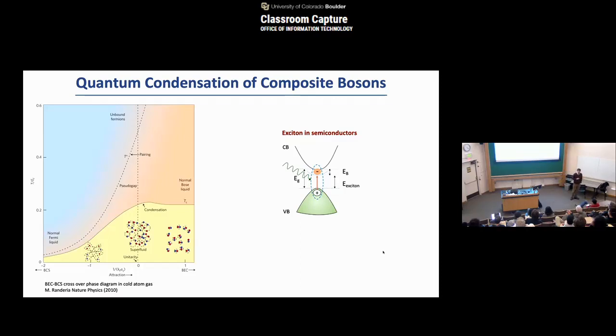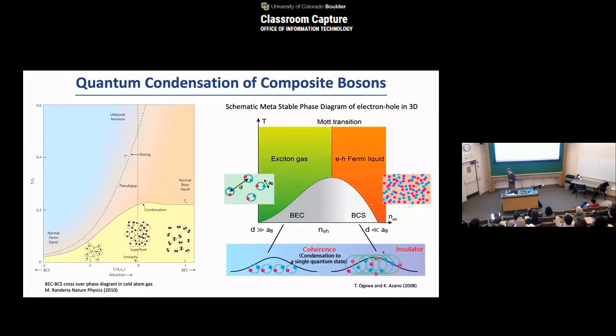Of course, the exciton as an excited state has a finite lifetime. But somehow, with some magic, if we make this exciton lifetime long enough, one can envision a phase diagram of this exciton. Indeed, at least in theory, people came up with a very similar idea: if you have a bunch of excitons and get to a low enough temperature, you can condense them into an exciton condensation. Depending on the exciton density, especially the distance between excitons compared with the size of the exciton, you can go from a BEC-like well-isolated exciton condensation to intermingled excitons, with distance comparable to the size of the exciton, where a BCS type of condensation is possible. In fact, it can be tunable by the exciton density, and there have been some discussions out there.